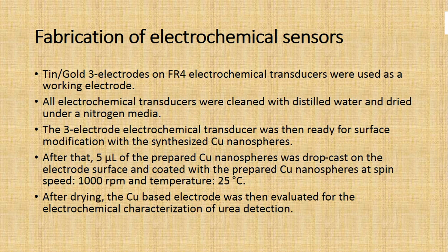Tin/Gold 3 electrodes on FR4 electrochemical transducers were employed as working electrode. All electrochemical transducers were cleaned with distilled water and dried under nitrogen. 5 microliters of copper nanosphere solution was drop cast on the electrode surface and coated at a spinning speed of 1000 rpm at room temperature. Urea detection was performed with the so-obtained electrode.